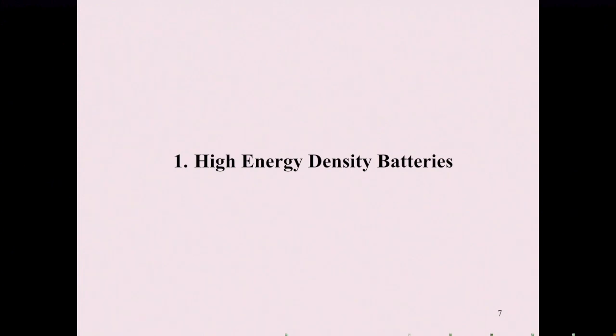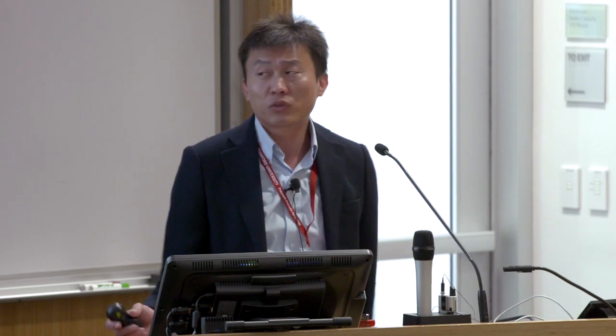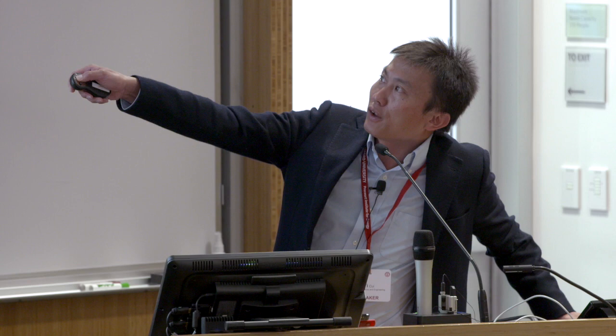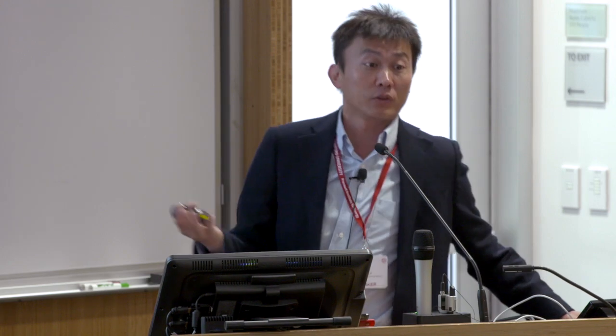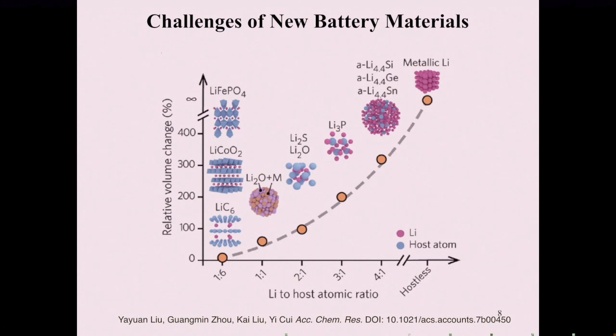The first one, this is the one I really like. I've been working on this right at the beginning when I joined the faculty. High energy density of batteries, how high can it go? It comes back to a very simple understanding or equation, basically general chemistry. So let's use lithium as an example. In order to increase the energy density, you want to store a lot more charges. That's lithium ions. So this is current technology using all this material. This is the plot we made. It's the atomic ratio of lithium to the host material structure. We only utilize one lithium per six atoms, roughly, of the host material. So you actually have a heavy weight, big volume.